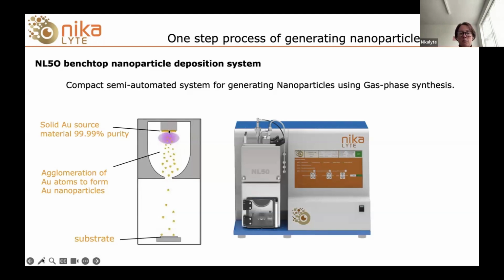We have a sputter target of material at the top here. A plasma is generated with argon gas in front of that, knocking atoms of, in this case, gold off the target. Those atoms coalesce and agglomerate to form nanoparticles as they travel through this aggregation or nanoparticle zone. They exit through the aperture and then into the bottom chamber, which is our sample chamber, and land on the surface. So you can see in this image, we've got the top chamber here, which is where the nanoparticles are formed, and the bottom chamber here, where we deposit onto a surface. And the sample, you can see just here at the bottom, inside the NL50 sample chamber.